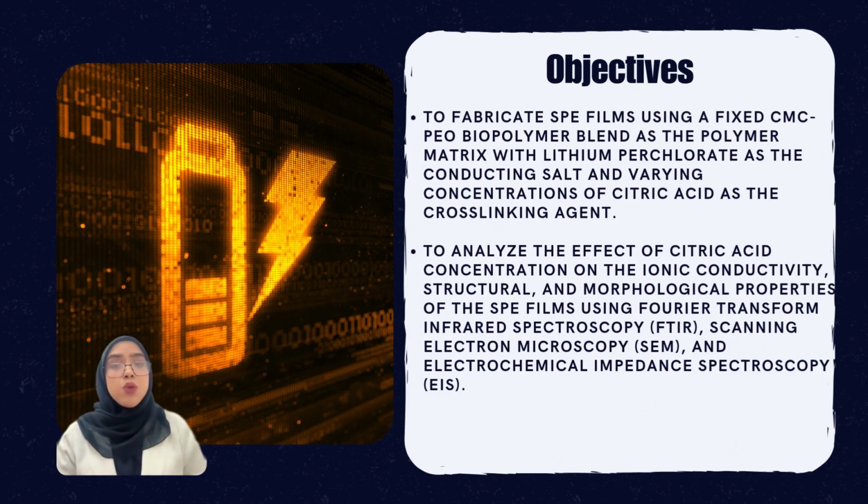Okay, in the experiment, we have two objectives. First, to fabricate the solid polymer electrolyte (SPE) using a fixed CMC-PEO biopolymer blend as the polymer matrix with lithium perchlorate, LiClO4, as the conductive salt, and also varying the concentrations of citric acid as the cross-linking agent. And second, to analyze the effect of citric acid concentration on the ionic conductivity, structural and morphological properties of the SPE using FTIR, SEM, and EIS.